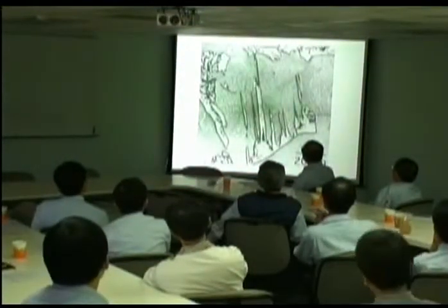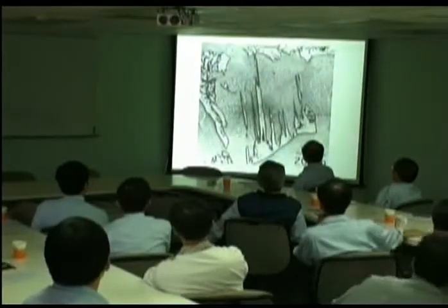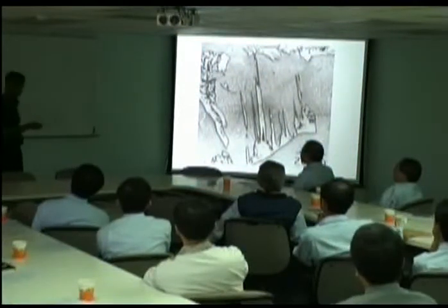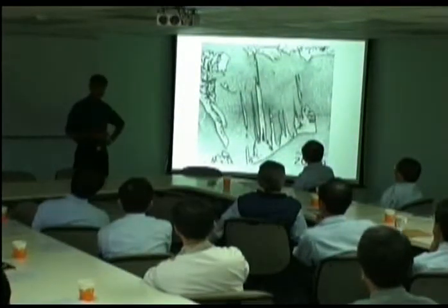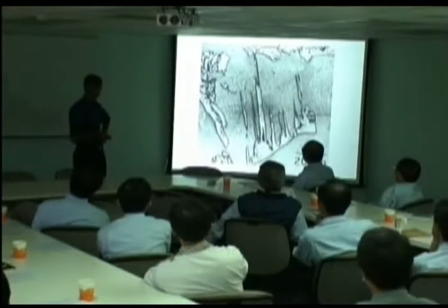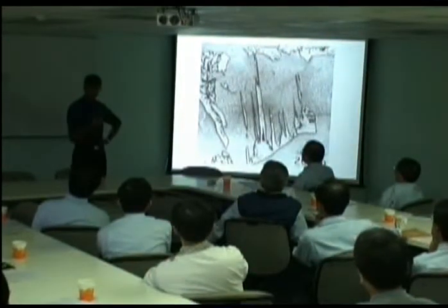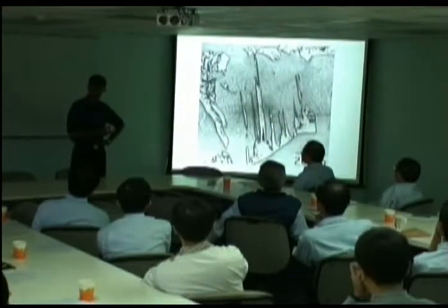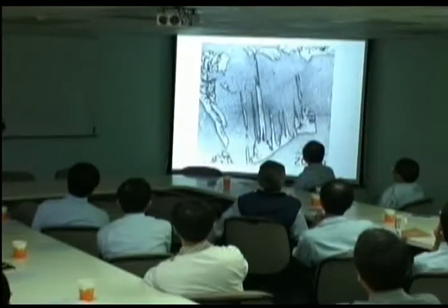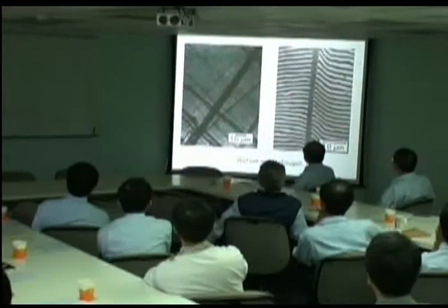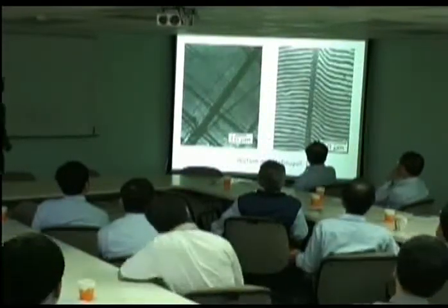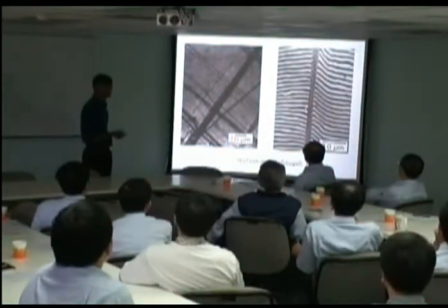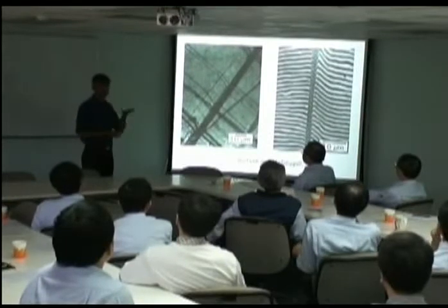This is a micrograph showing you Widmanstätten ferrite. Notice one thing. This is again an optical micrograph. This time it doesn't appear dark. It's etching nice and white. There isn't structure inside those plates, as in bainite. Watson and McDougall did measurements of the shape deformation, and this is an interference micrograph showing you, again, there is a shear deformation.